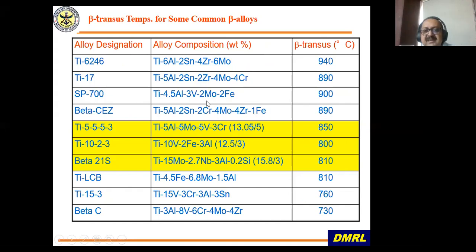SP700 is a superplastic Japanese alloy, and it is superplastic at much lower temperature compared to Ti64, but it has somehow not caught up people's imagination. But it's still there anyway. It's like 6.4. And these are again 1023, beta 21S, 5553, which is a variation of the Russian alloy VT22. And these are the beta transus lines. And you can see as you go to richer alloys, beta transus temperature decreases.